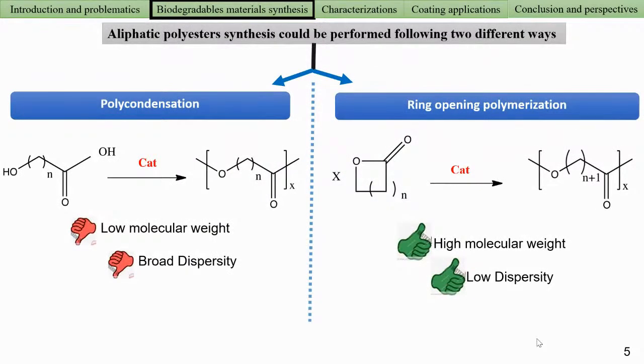To prepare this kind of polymer, there are two kinds of methods: polycondensation, which is less expensive, or ring-opening polymerization, which is much more expensive. But polycondensation leads only to low molecular weight with broad dispersity. This gives the polymer no industrial application because of the low molecular weight. With ring-opening polymerization, we can prepare a polymer with high molecular weight. We can control the molecular weight by controlling the ratio between monomer and catalyst, achieve specific end groups at the end of the polymer, and prepare block and multi-block polymers.